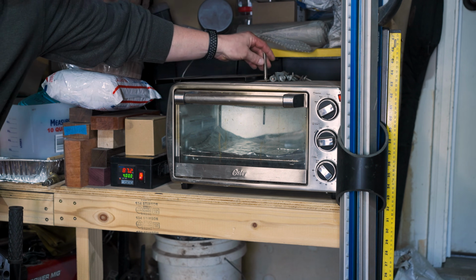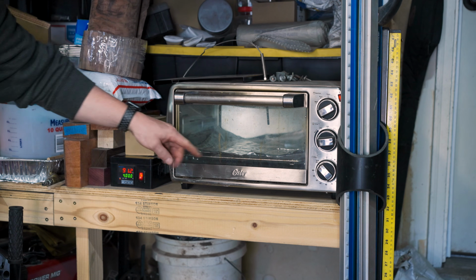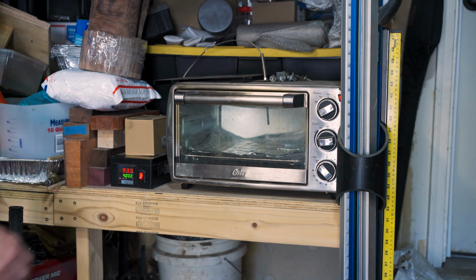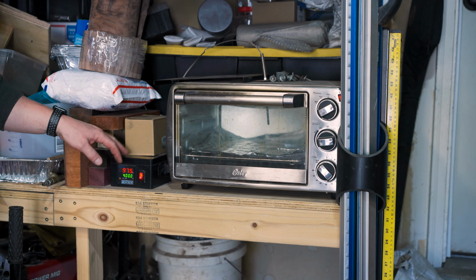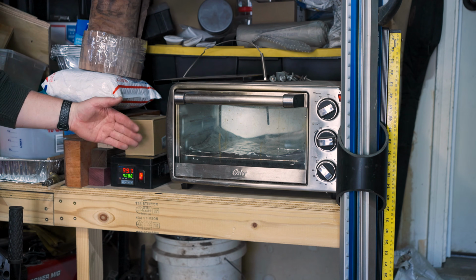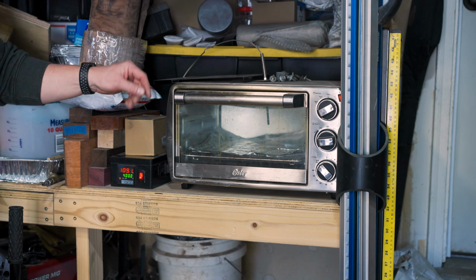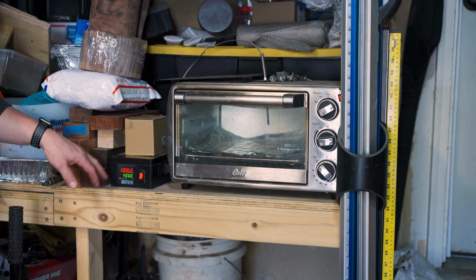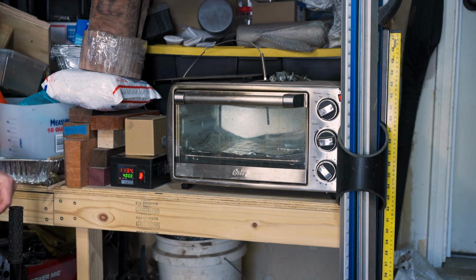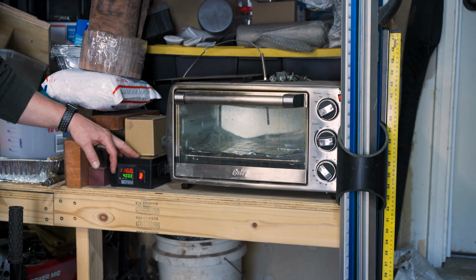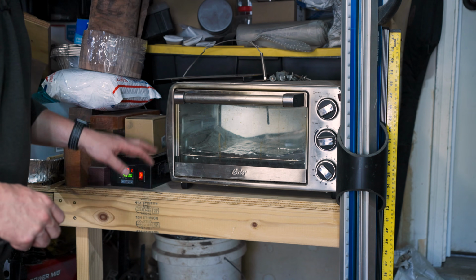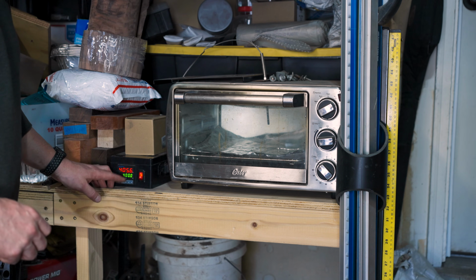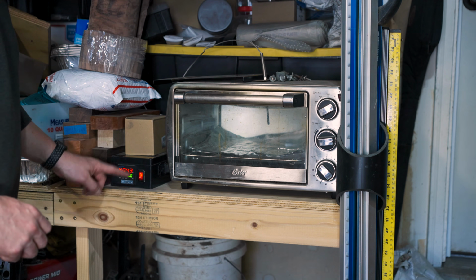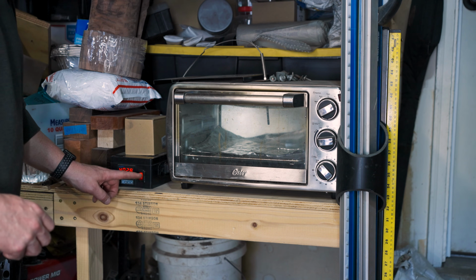I've got a thermocouple in the top here that runs down inside, right in the middle of the area. And this thing does a really good job. The higher the heat, the higher the temperature, the more accurate it stays. But for a toaster oven, it does well. And this PID was pretty inexpensive to make. But like I said, I use this for a lot of things. I've got another toaster oven that I do my stabilizing with my handle material, and it works really well for that as well. So this has gotten up to temp and stabilized quite a bit. When you first turn this on, it'll go way past the heat and then come back down below, and then it'll start stabilizing in there.